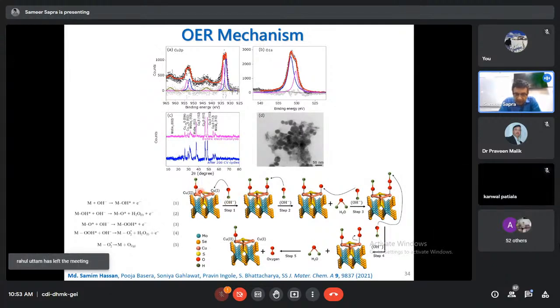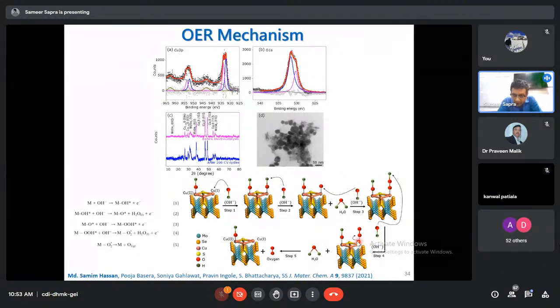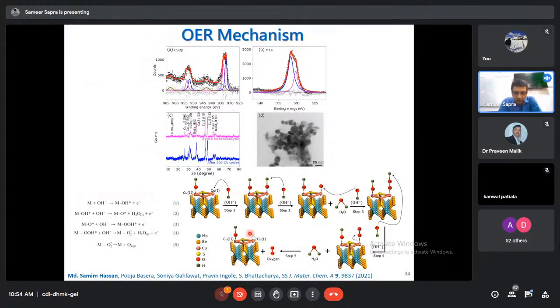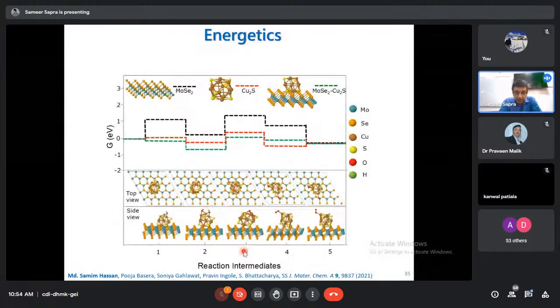So both of these sites are essentially identical. Anything could be copper 1, copper 2. So now you see both of them have become copper 2. And another hydroxide attacks and makes the superoxide, and the superoxide releases oxygen, and that's how you get oxygen and retrieve your catalytically active sites as they were. Okay, the same thing, you'll see all these reaction pathways.